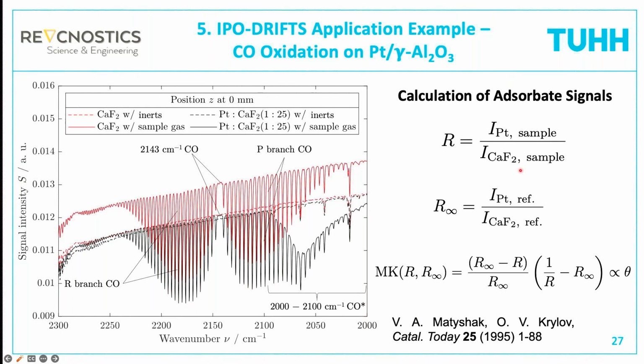And now we can calculate the reflectivity of the sample, always with respect to calcium fluoride, of the catalyst with respect to calcium fluoride under the sample gas atmosphere. So if the gas comes from the reactor, and then under the reference gas, in this case, it was argon. And now we have calculated from these reflectivity values the so-called Matyshak-Krylov function. I have given you also the reference here.